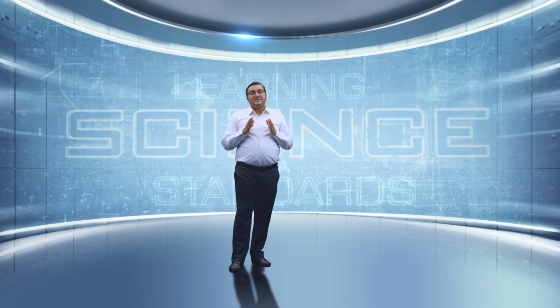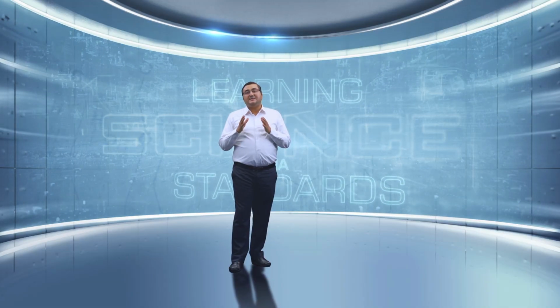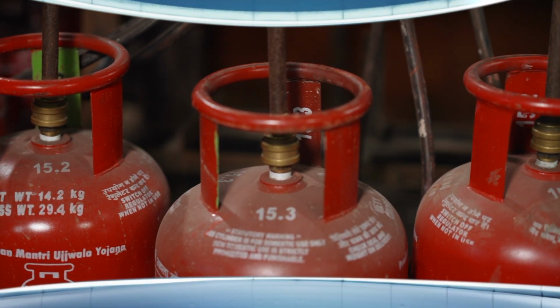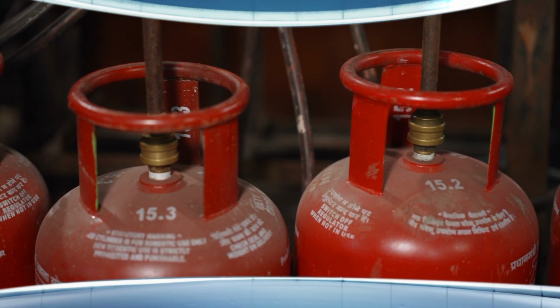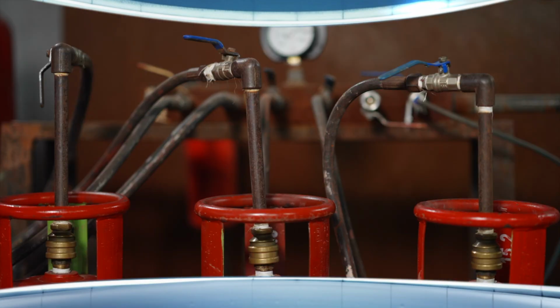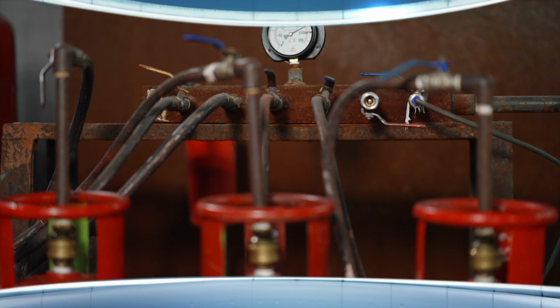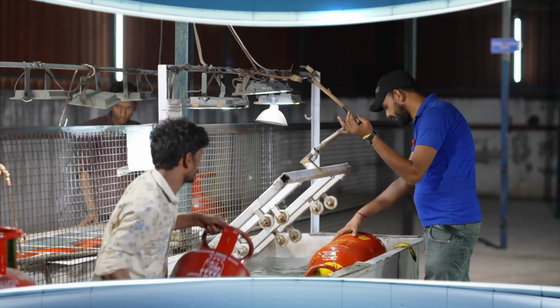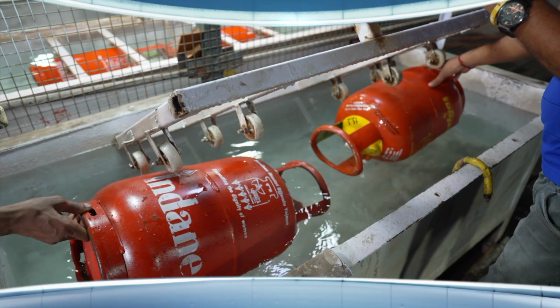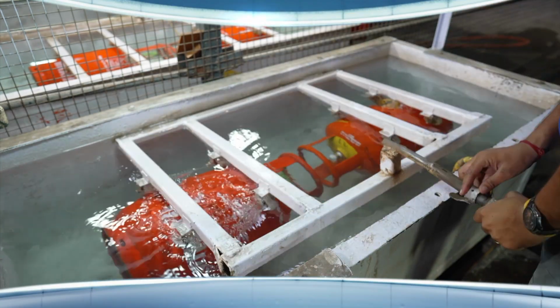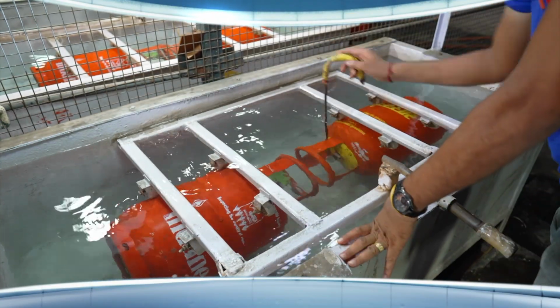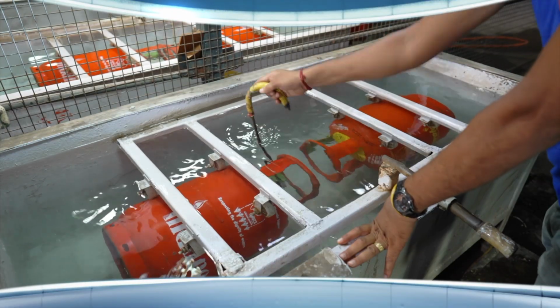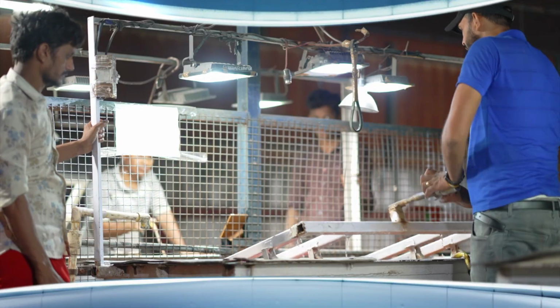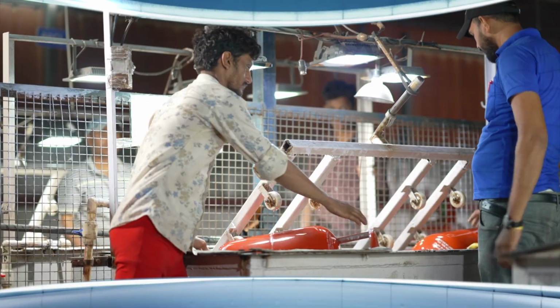Another important test is the pneumatic leakage test. In this test, pressure vessels such as cylinders are tested for strength and leakages by filling the cylinder with air, pressurizing it and maintaining the pressure for some time. The cylinder is subjected to air pressure of not less than 1.18 megapascals for a period of 1 minute while immersed in water and shall show no leakage from the body of the cylinder. The cylinder is considered as failed if there is any leakage which is detected by the air bubbles inside the water at the site of leakage.